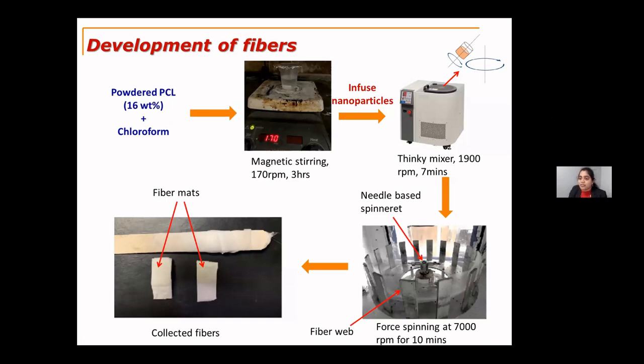So I chose 3 weight percentages: 1 weight percent of hydroxyapatite, 2 weight percent of hydroxyapatite, and 3 weight percent of hydroxyapatite. So these are 3 samples. I infuse those nanoparticles in the solution. 1 weight percent means for 100 grams of polycaprolactone, we consider 1 gram of hydroxyapatite. 2 weight percent means for 100 grams of polycaprolactone, we choose 2 grams of hydroxyapatite. So for the polycaprolactone considered here, we choose 1, 2, 3 weight percentages of hydroxyapatite.